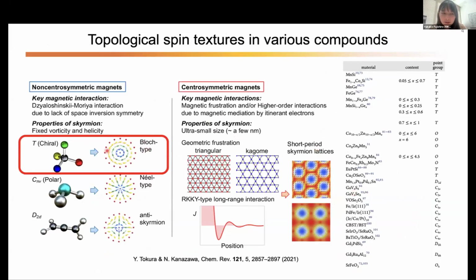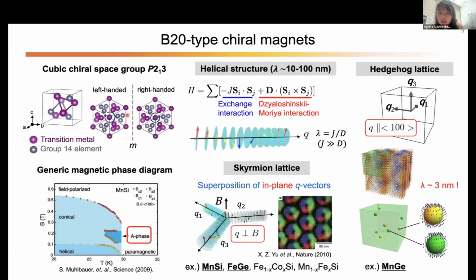Nowadays there are so many materials where these kinds of topological textures are experimentally identified. But today I would rather like to focus on a very basic and the most famous material system, which has a chiral crystal structure and hosts Bloch-type magnetic skyrmions. The target material belongs to the family called B20-type chiral magnets. These materials crystallize in a cubic chiral space group and are composed of a transition metal and a group 14 element with a 1-to-1 ratio. It has left-handed and right-handed crystal structures. Because the inversion symmetry is broken, there's a spin interaction called Dzyaloshinskii-Moriya interaction, which tries to rotate the spins.